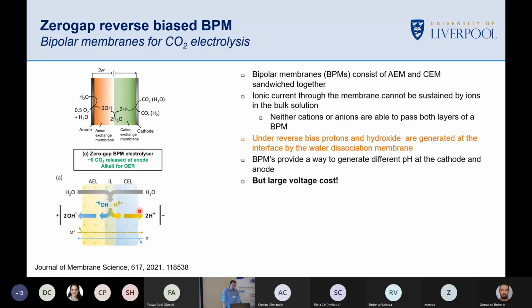Everything comes at a cost, and the other big benefit, of course, is that we will potentially still get a bit of carbonate formation. It is possible local pHs could rise high enough at high current densities, but we won't get much crossover. So carbonate will not transfer efficiently through the cation exchange layer. So there's a lot of benefits.